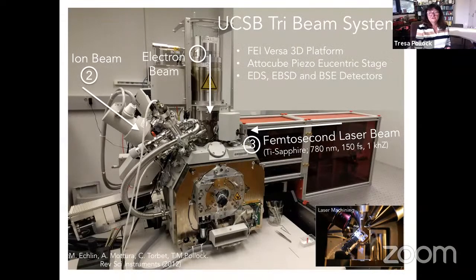Now, to do that, we obviously need to look at the material in 3D. And so I show here a system that we've developed over the last decade or so since I've been at Santa Barbara. And we call this the tri-beam system. What this basically is, is a Thermo Fisher TFS FIB microscope. And that means we have an electron beam and an ion beam. And what we've done is coupled a femtosecond laser with this microscope. So a titanium sapphire laser that operates at 780 nanometers. And this is a femtosecond laser. And I'll explain in a minute why it's important that we use femtosecond lasers for this sort of thing.